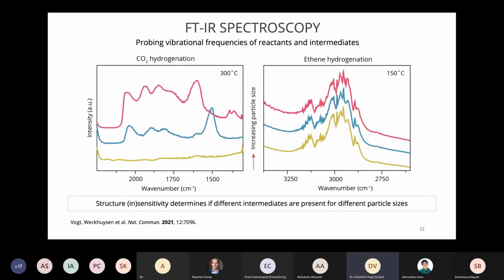So, okay, we observed this lattice expansion. Then we wanted to know in more detail, in more chemical detail, and later on also in more electronic detail, what happened to these nanoparticles. So now we're moving back to supported nanoparticles, so nickel on silica, and we checked again CO2 hydrogenation versus ethene hydrogenation here in IR spectroscopy. With IR spectroscopy, of course, you probe vibrational frequencies, and that means that often you're able to observe reaction intermediates on the surface of supported metal catalysts.